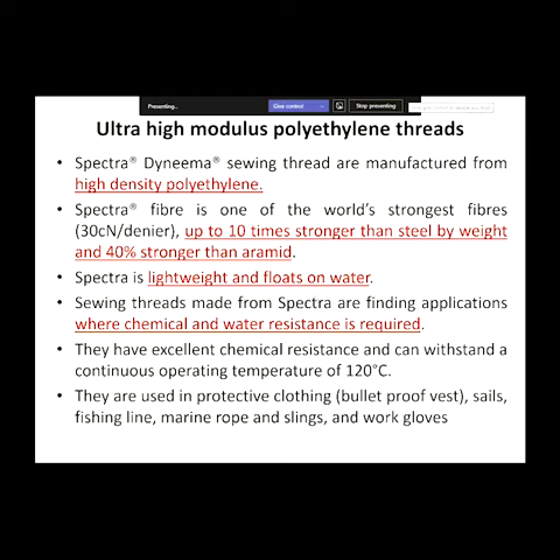This Spectra fiber is one of the strongest, which has around 30 cN per denier, up to 10 times stronger than steel by weight, and also 40% stronger than the aramide, especially the Kevlar fiber, the para-aramide fiber. And its density is very low. It can easily float on water. Another plus point is it has good water resistance and chemical resistance. Many of the chemicals will not affect this polymer. And temperature resistance is only up to 120 degrees because it has a low melting point.